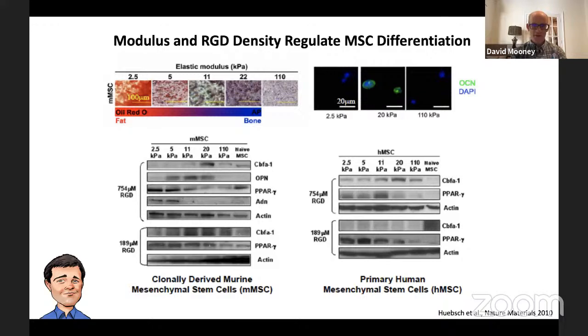In gels that were a little bit stiffer, the cells became osteoblasts or bone-forming cells. And in the really rigid gels, they actually didn't differentiate at all. And all the rest of the data here is just some molecular characterization and confirmation of the fate of the cells being regulated by the mechanics in concert with the density of the adhesion ligands. So this definitively said that we could indeed regulate cell fate in 3D with mechanics.